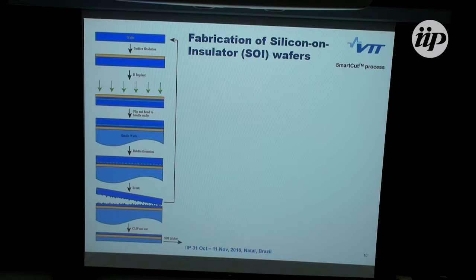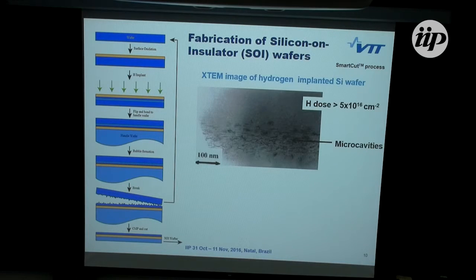and then this wafer will be polished. This is a cross-sectional TEM image of a hydrogen implanted silicon wafer. The doses are quite high, and the hydrogen forms these microcavities, and then when this is heated up, they form bubbles, and the bubbles progress in this direction and break the wafer. And this is actually the smart cut process, which is the most important nowadays.